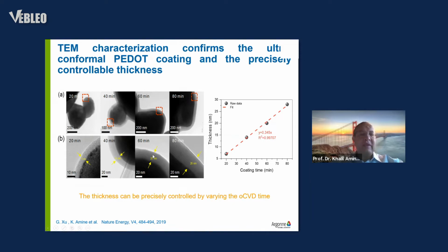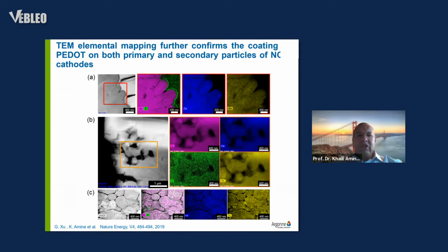Now, how about inside? We want to have evidence that we also have protection inside the particle, the primary particles, what we call the grain boundaries. So we did a cross section of a particle, ran it by TEM, and looked at EDX for the signature of sulfur. Sulfur is green here. You can see we have a uniform coating at the surface of the particle, but also inside the particle, there is a tremendous amount of green, that's sulfur. This is polymer PEDOT inside the particle and also in the grain boundary. So we have clear evidence that we basically protect the whole particle.